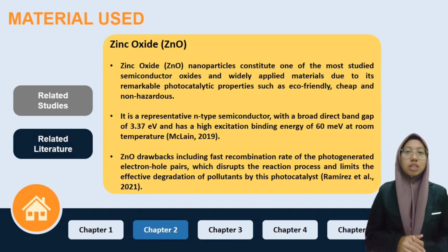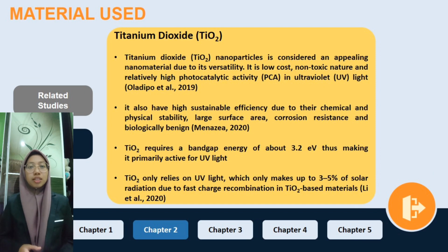Zinc oxide drawbacks include the fast recombination rate of the photo-generated electron hole pairs, which disrupts the reaction process and limits the effective degradation of pollutant by this photocatalyst. Next is the titanium dioxide. Titanium dioxide nanoparticle is considered as an appealing nanomaterial due to its versatility. It is low-cost, non-toxic in nature and has relatively high photocatalytic activity in ultraviolet light, according to Oladipo 2019.